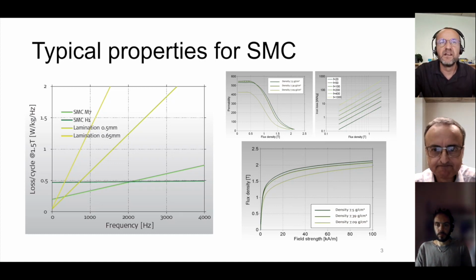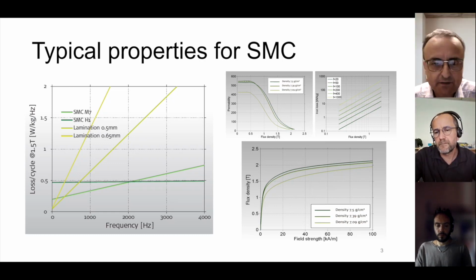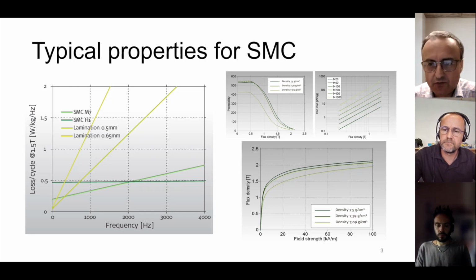Indeed. Yeah, in automotive, they go even thinner, don't they? It depends on the frequency and on the target that you have in terms of losses. If you go very, very thin, you can even have applications in which you go below 0.1, but those are tapes rather than laminations, because they become very flexible. Then you need something to put them together and keep them in the right shape, because otherwise you will have something just resembling paper sheets. Okay. Yeah.